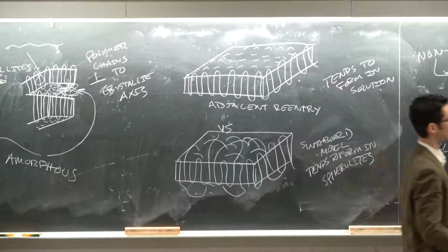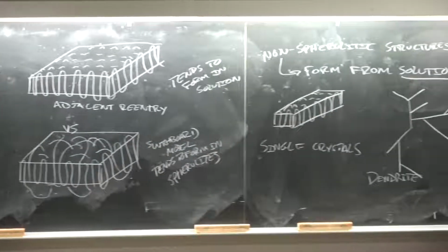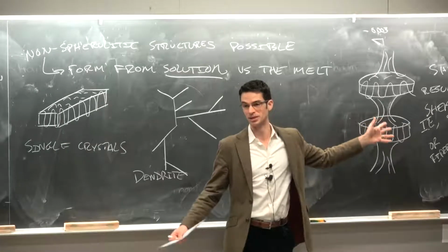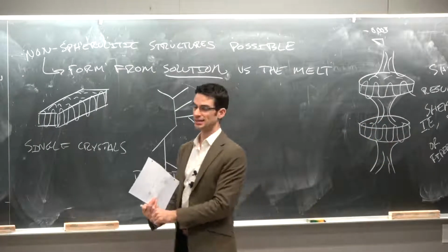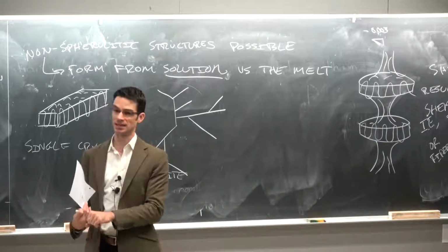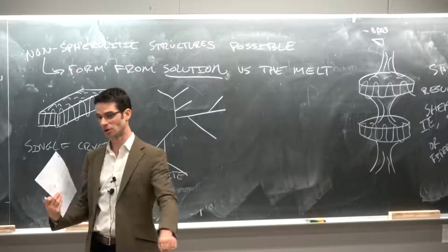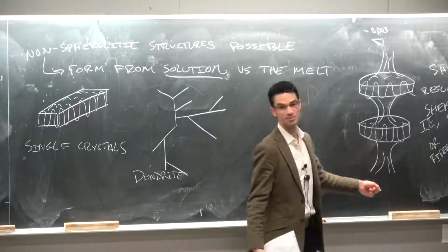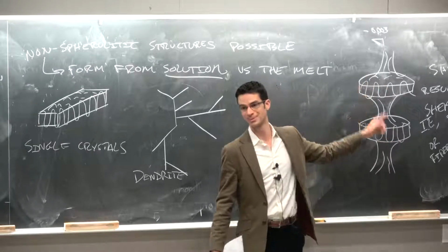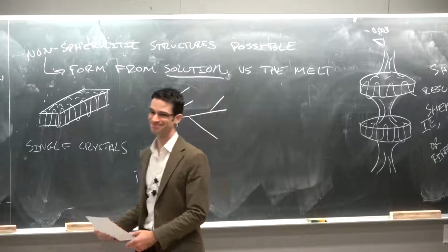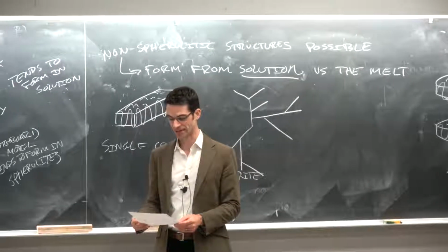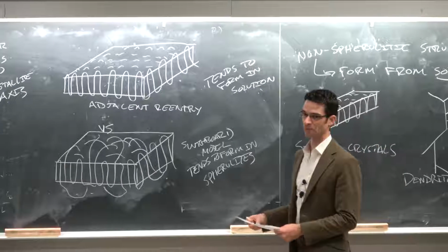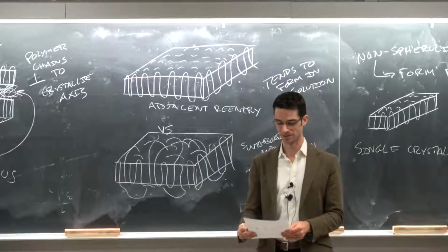You certainly have alignment between the crystallites, and in some cases you might have structures like this, but the tensile strength of nylon is more a result of the drawing process, and I don't know if you get the kebabs. It might just all be shish, might all be kebab. Certainly have some other structures in there, but primarily it's just because of long drawn out structures.